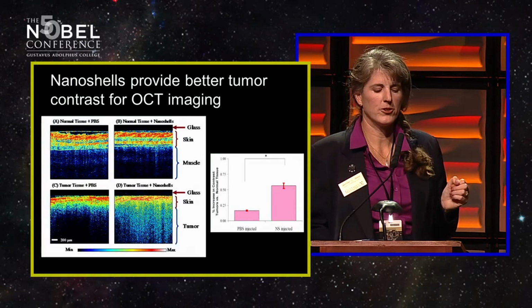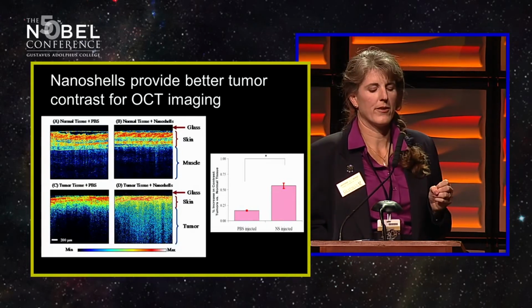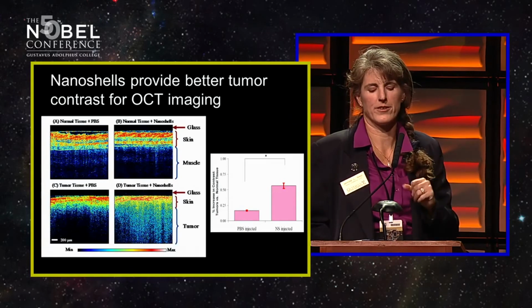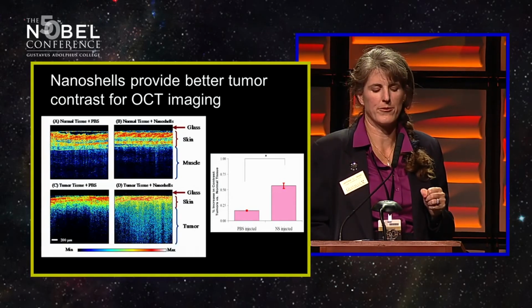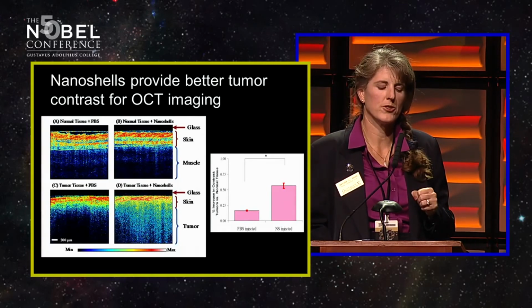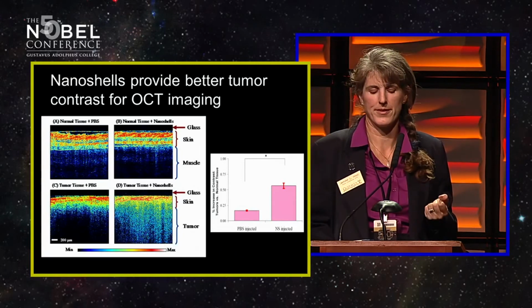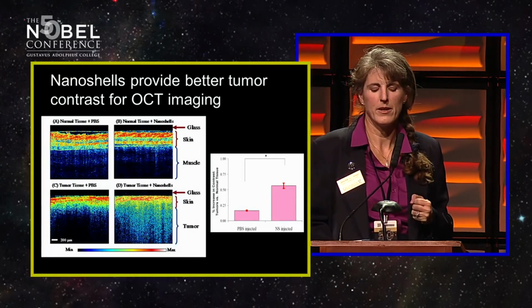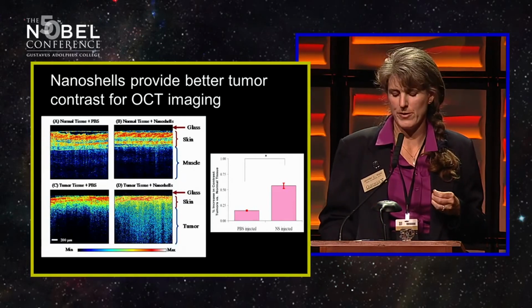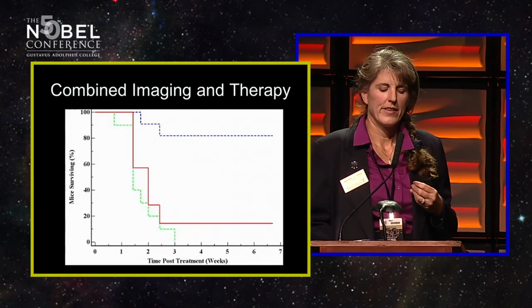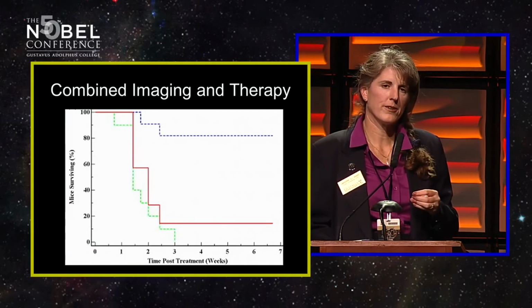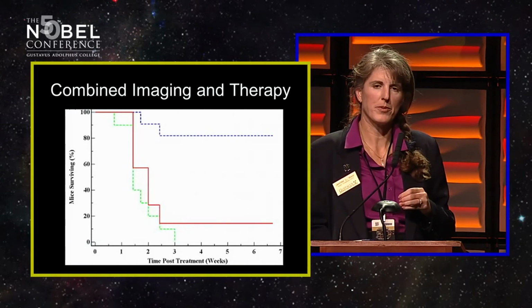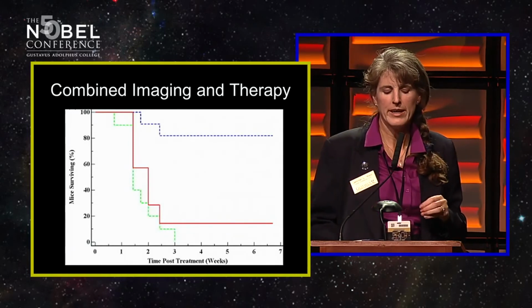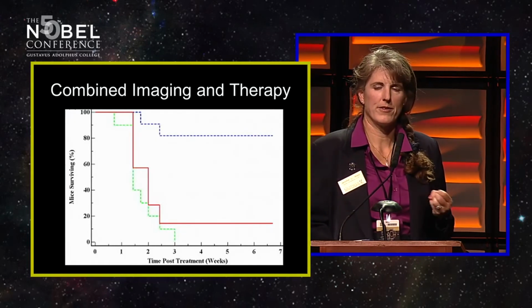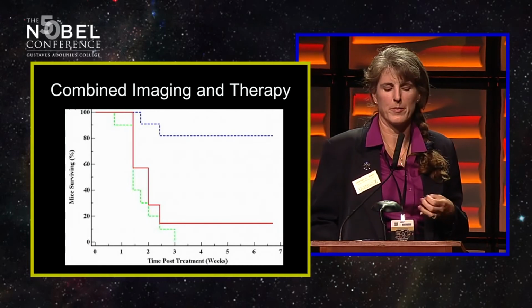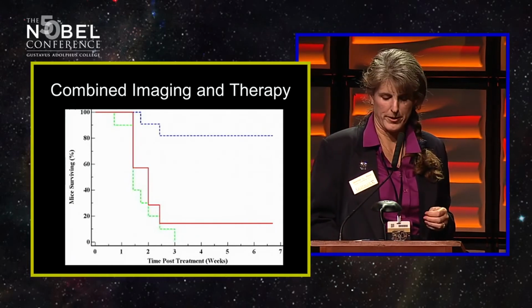If we compare normal tissue with or without nanoshells, so on the left column is without nanoshells, the right column is with nanoshells, we see essentially no differences in those images. But if we look at the tumor tissue with and without nanoshells, we start to see enormous differences in the tissue. And when we do the image processing, we end up with signals that become much more effective for diagnosis of the tumor. And then if we look at survival of these animals over time, with these particles that are now only 50% absorbing, we still had 80% of the animals survive tumor-free long-term. And so we think that we still have something that is a very good cancer therapy, but also now gives us the imaging modalities as well.